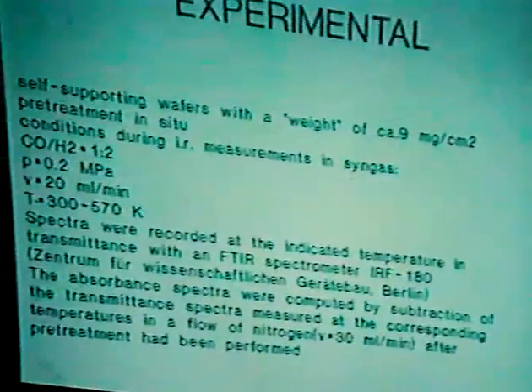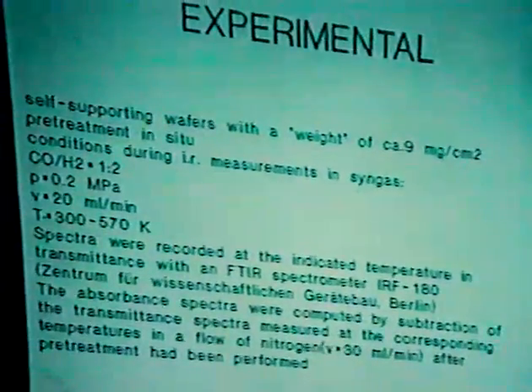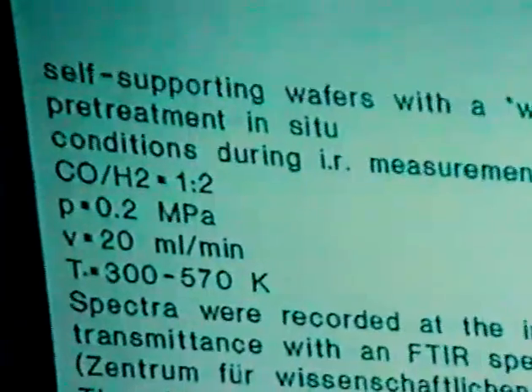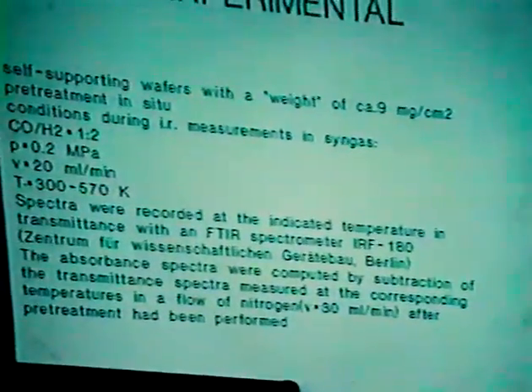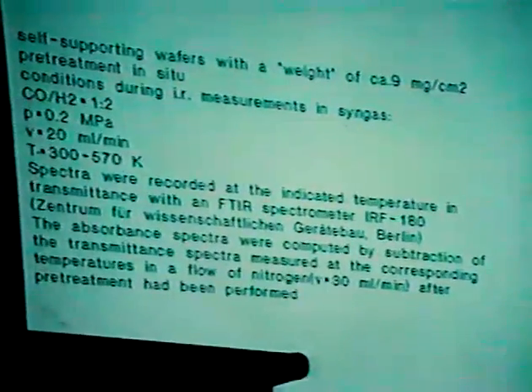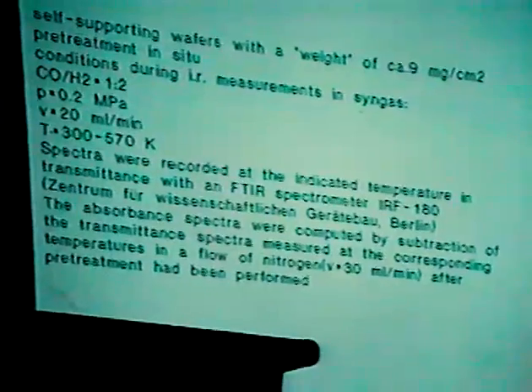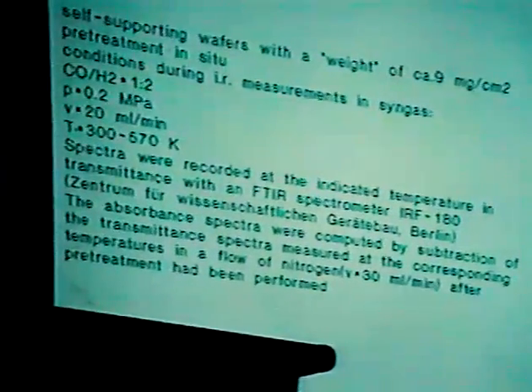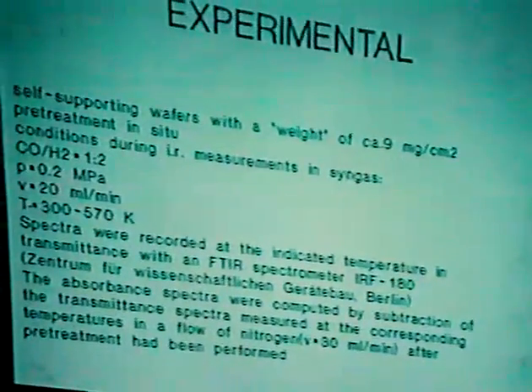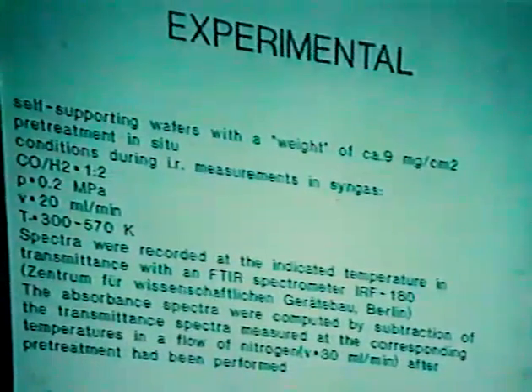In order to investigate the adsorption behavior of carbon monoxide on these differently dispersed rhodium particles, we studied on self-supporting wafers after pre-treatment in situ during IR measurements in flowing syngas. All the spectra were recorded at the indicated temperature in transmittance with a Fourier transform infrared spectrometer, and the absorbance spectra were computed by subtraction of transmittance spectra measured at corresponding temperatures in a flow of nitrogen.